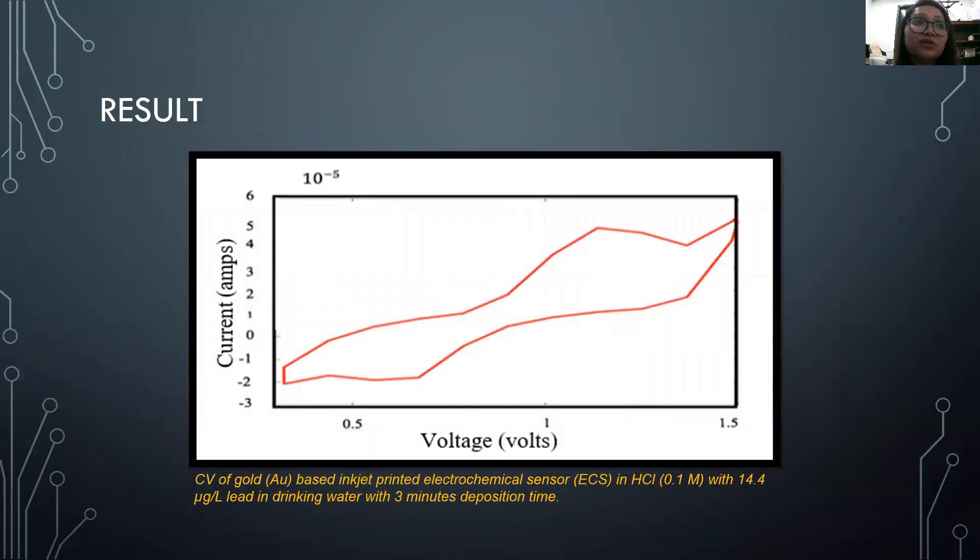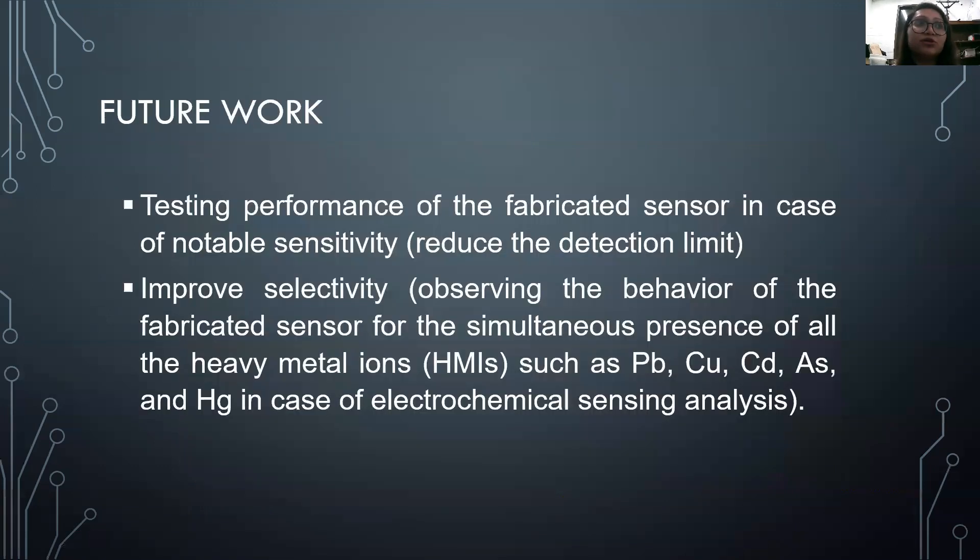This is our final result in case of 14.4 microgram per liter lead, which is below the US EPA-approved lead level of 15 microgram per liter, for our fabricated inkjet-printed electrochemical sensor.